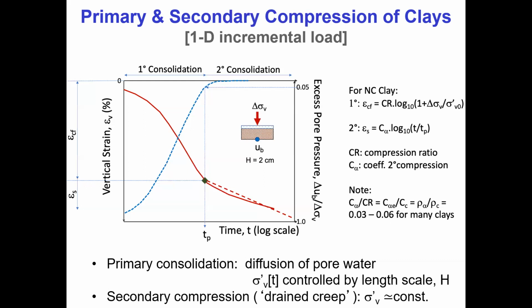That is characteristically occurring at some time frame we say is the time for primary consolidation. We measure strains through that time frame, and we have the strain at the end of primary consolidation, epsilon_cf, and then the strains that occur after that, this being the measured result, we say are secondary strains, epsilon_s. And then you can see all the analysis and diagnosis of how we get parameters from this. So the primary consolidation we get from the applied load and the compression ratio of the normally consolidated soil. And you can see the secondary from C alpha and time relative to the end of primary. And we generally are assuming a straight line approximation on a log scale.